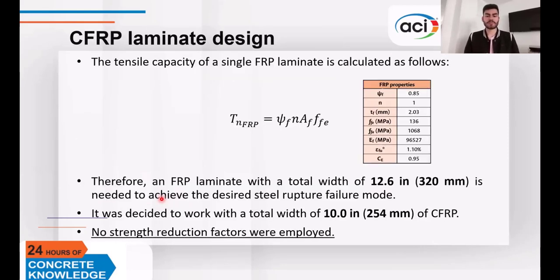Regarding CFRP reinforcement, its capacity due to tensile loads is as follows, which results in a total required width of 12.6 inches or 320 millimeters. However, a decision was taken to reduce this width to just 10 inches or 254 millimeters to assess if it was possible to obtain the desired results with a smaller area of reinforcement. Also, important to note that no reduction factors were employed.